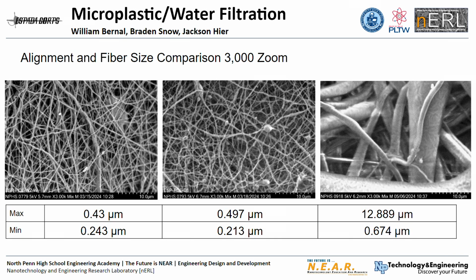Now, when we were wondering why, we really had to take a look much closer up, all the way down to 10 micrometers. And with this, we were able to see the total range that we really had of the sizes, and we think this is why we were able to catch so many more plastics. As you can see, we had up to 12 microns caught with the Forcespun one, whereas the other two have very small fibers, and we're catching less overall because of the lower range.